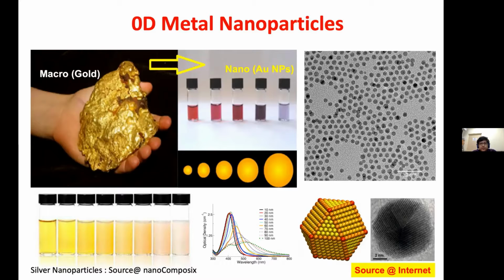But interestingly, if you reduce the dimension of gold, suppose you make a gold nanoparticle of 5 to 10 nanometers, its color changes. Here you see the gold nanoparticles, but they have different colors, red and pink, based on the dimensions. Here are some beautiful gold nanoparticles, and silver is generally white, but you see the silver nanoparticle colors are yellow and some pink regions. These happen due to the electron distributions of those particular materials.